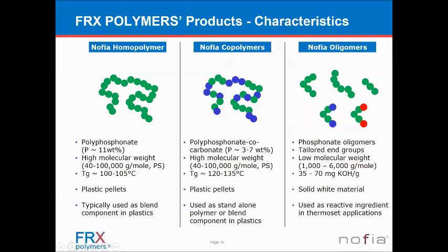Because of the chemistry that we use, we have a lot of flexibility to make different types of materials. So we have one group of materials which are a polyphosphonate co-carbonate material, where we have different levels of phosphorus, and we can again make different types of molecular weights. And these are specifically designed to be used in polycarbonate applications, and they can actually be used by themselves. So you can extrude sheets out of them, you can injection mold parts out of them, and you basically have an inherent flame retardant polycarbonate.